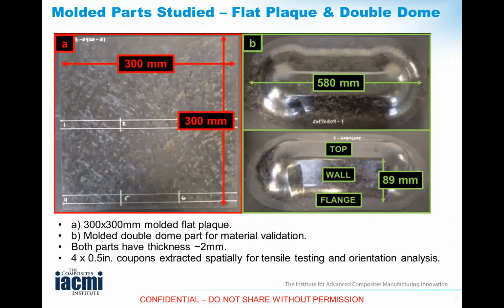This slide shows you an example of a molded flat plaque on the left side and a complex component, in this case the double dome, on the right-hand side. And fundamentally our challenge compared to metals is the following. Much of the material specifications from metals is based on coupon tests from flat specimens that then extend to modeling and simulation. Because of the grain size and typically the processing of the plates, very rarely do you have highly textured surfaces, so more or less you're starting with a random orientation of the grains, and then subsequently anisotropy is not often considered in metals.